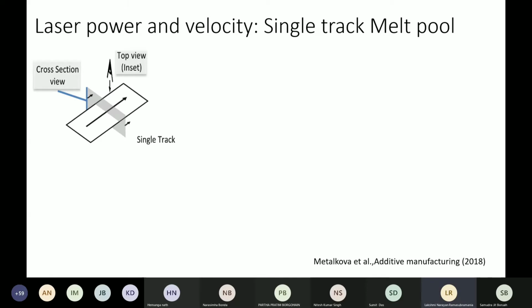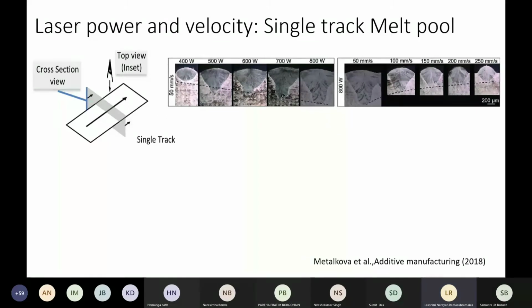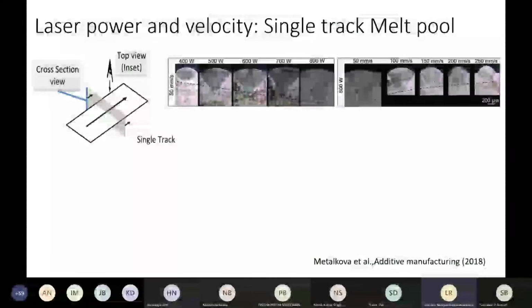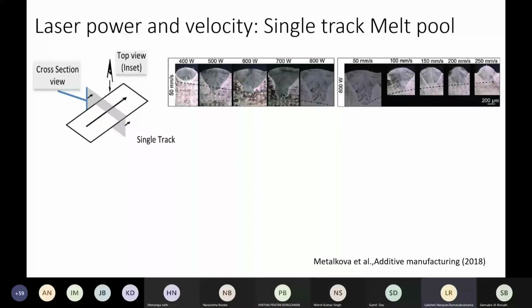What we are going to look at is something called a single track melt pool. So you are assuming that a laser is running over a plane in a straight line, and I am going to cut the cross section of this material and look at it in a metallographic or an optical microscope. What you see here is that this cross section will show you a melt pool, and immediately you can recognize it is very similar to what you see in welding. In welding also you see a similar weld bead. So this is a process which is nothing but welding which is upscaled to build a component.